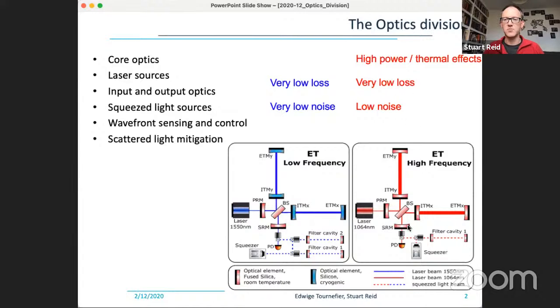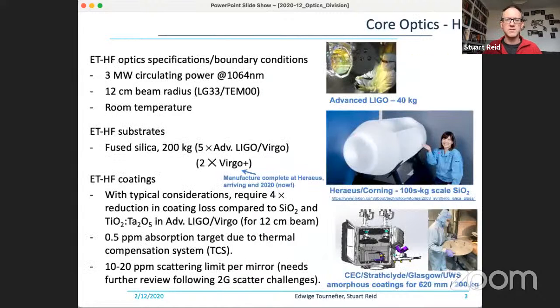And then ETHF, where we have the added challenge of very high optical powers within the Fabry-Perot cavities. If we have a look at the boundary conditions that we're expecting to operate within for ETHF, we have 3 megawatts circulating power within the optical cavities at 1064, expected to use 12 centimeter beam radii on the mirrors, and this will be at room temperature. Substrates, as has already been discussed, fused silica at 200 kilograms for the test masses.